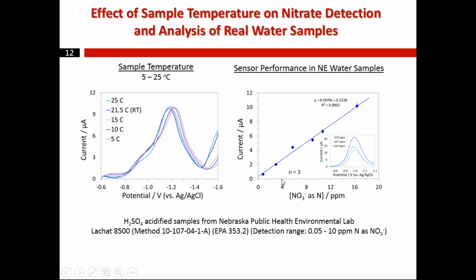And lastly, we calibrated the sensor, and we did this with the water samples that we got from the Nebraska Public Health Environmental Lab. These water samples were real water samples that were collected from farms all around Nebraska, and the concentration of nitrate in these samples was evaluated with other techniques. As you can see, we could get a very nice linear calibration curve for the concentration of nitrate with this sensor. And if you think of the MCL level of nitrate, which is 10 ppm, you can say that 10 ppm is within the linear range of this sensor. Therefore, the sensor can be used for detection of nitrate in the water samples. Furthermore, the linear range of the sensor is also comparable to the EPA-approved method, so you can say that the method can potentially be used as an alternative method for detection of concentration of nitrate.